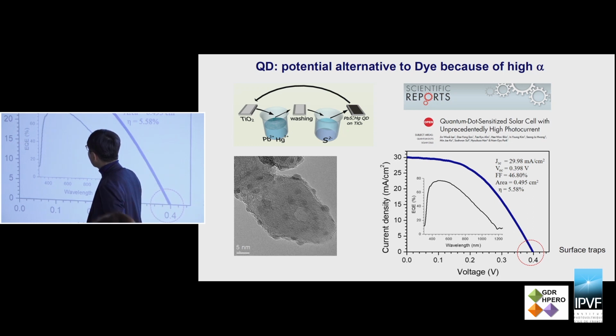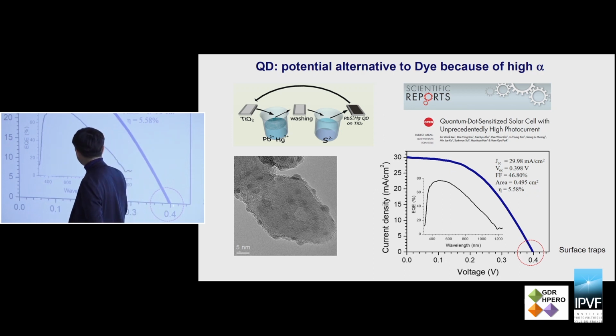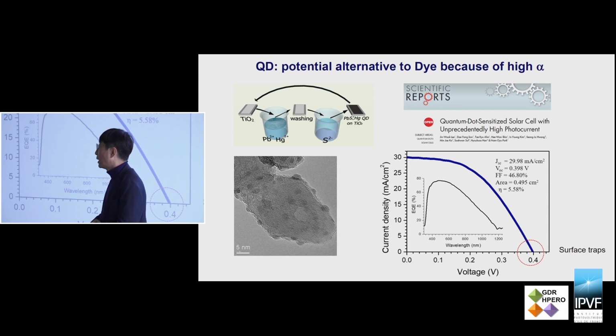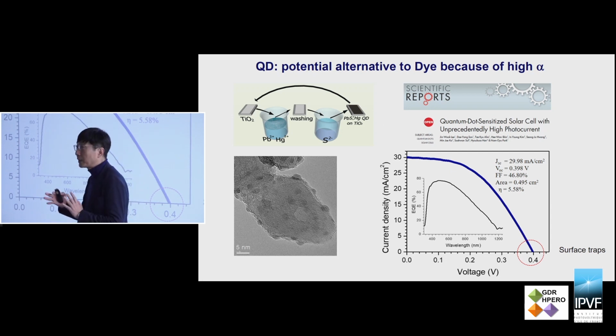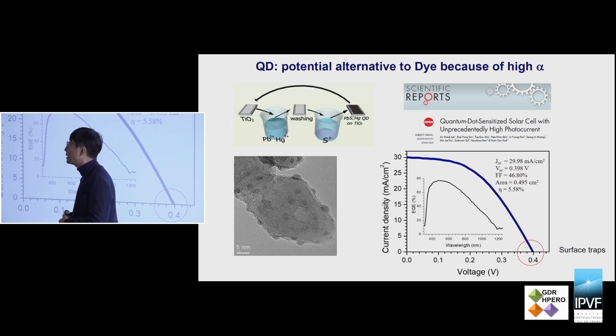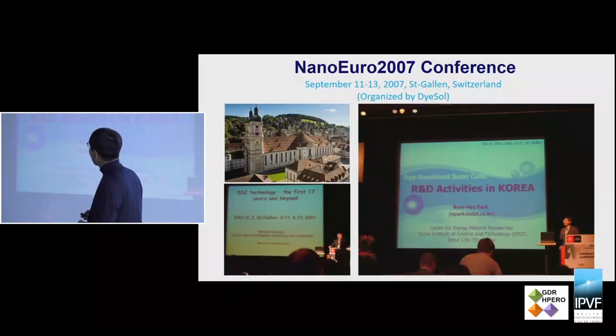We found that the photocurrent density is pretty good, approaching the theoretical value. However, the open circuit voltage is 0.4 volt, which is 0.7 volt lower than the band gap energy. That means there is a voltage loss of 0.7 volt. So this material actually cannot overcome the existing sensitizer such as N719, while searching for better candidates to replace the N719 sensitizer.